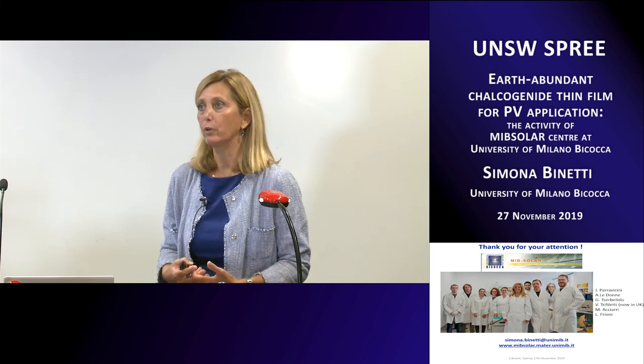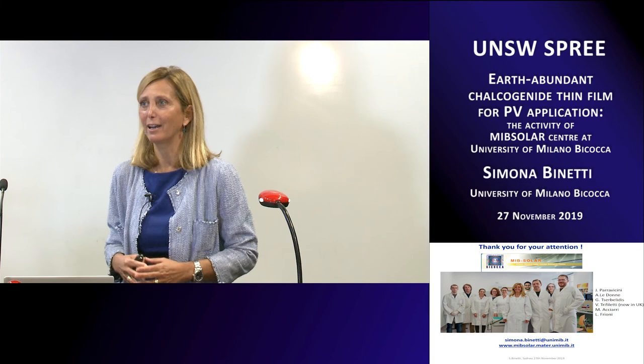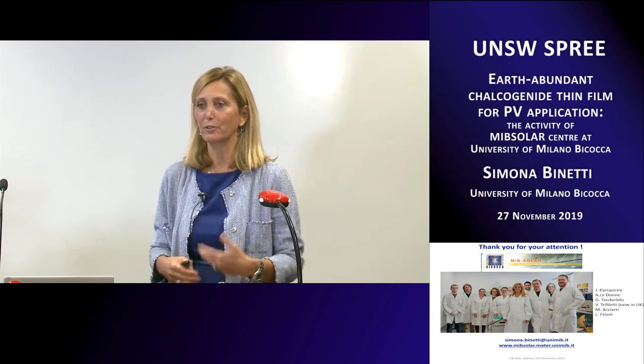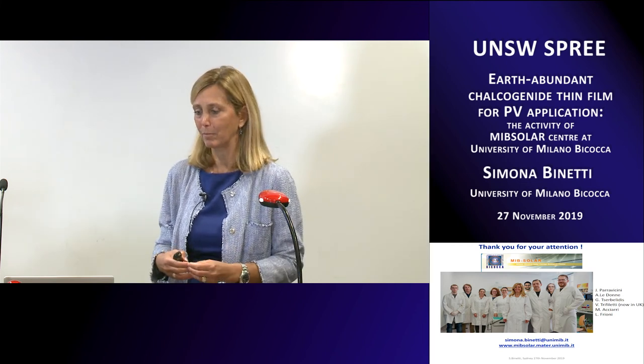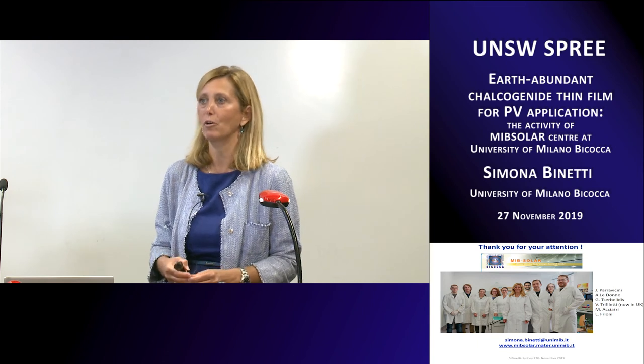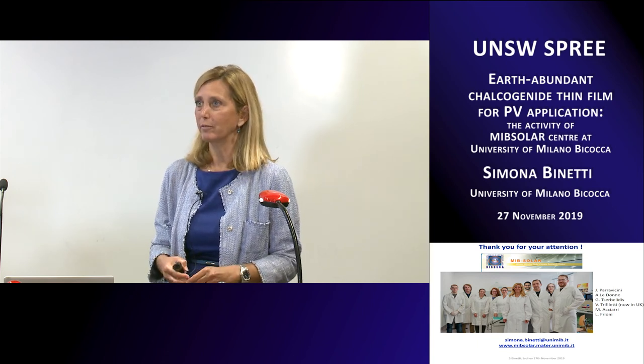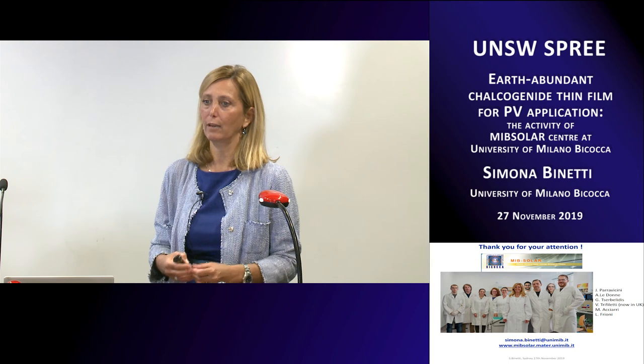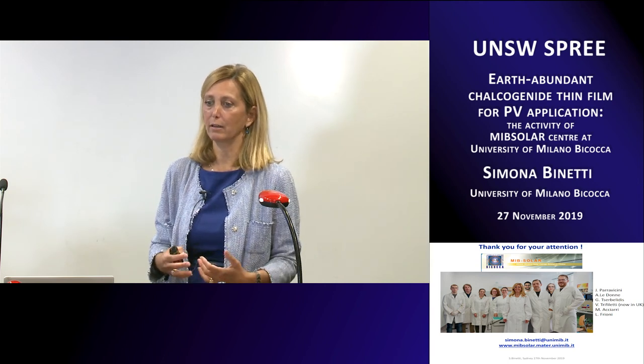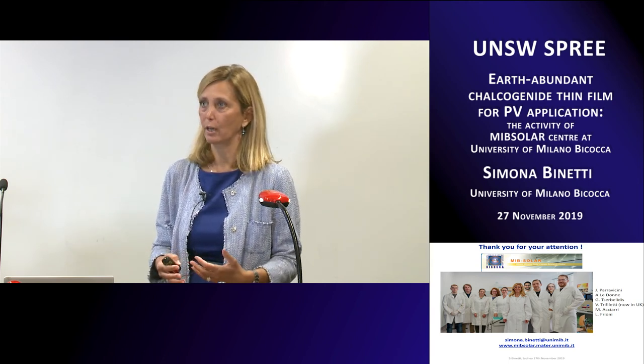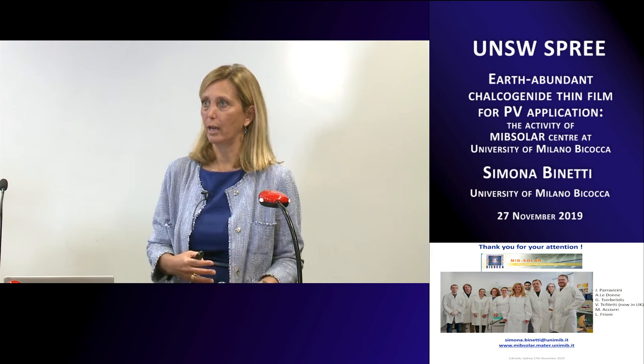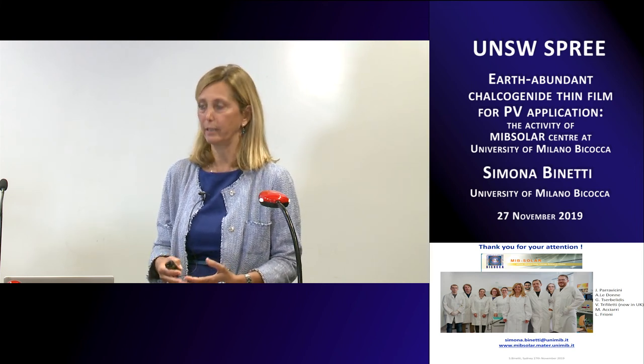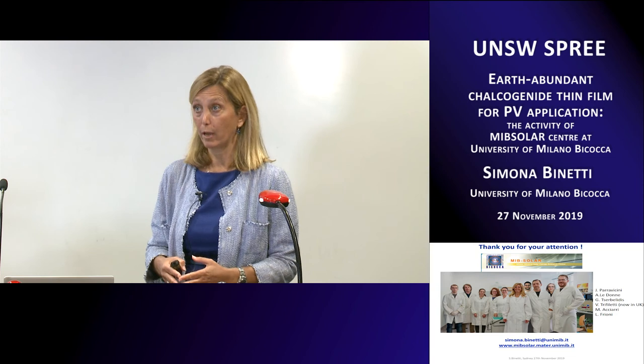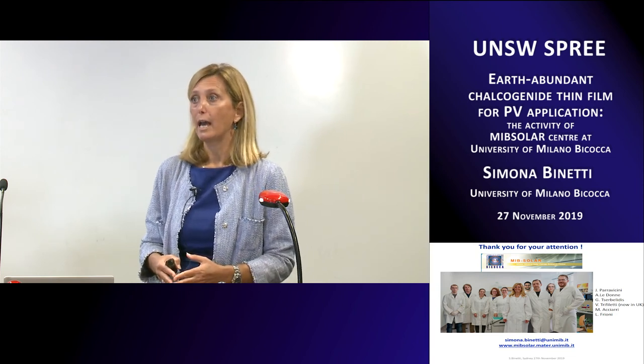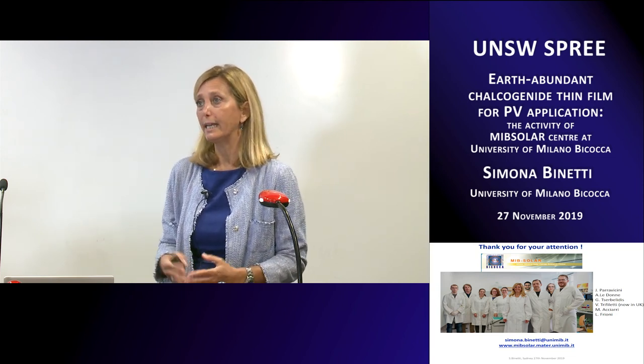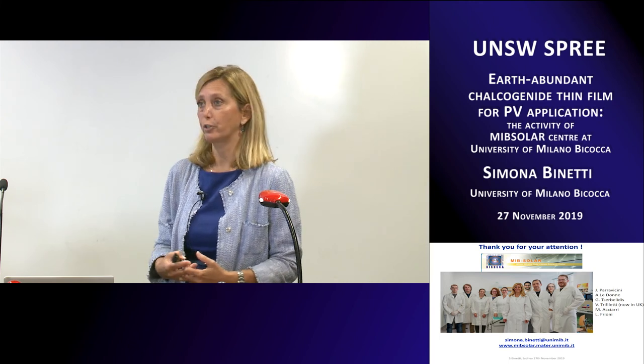But of course, we know that iron is not the best element because it can be diffused also in the bottom layer and so on. So this was our first attempt, and what we wanted to check is if our method is very suitable for changing the composition very easily, so we're starting with iron acetate. But we are working also on germanium, that is much more interesting. And the idea is to use the same process also for CZTS.